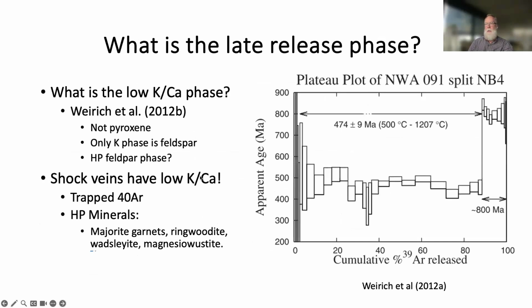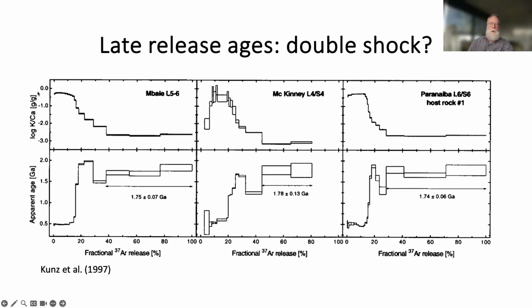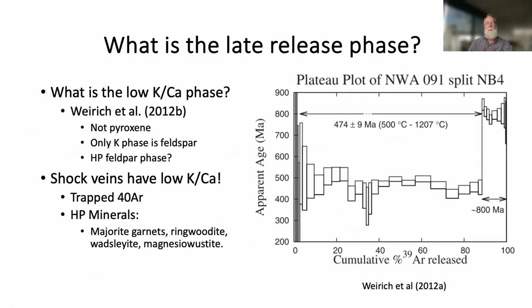A colleague, John Weirich, looked into this. He did his PhD with Tim Swindle, and he was really curious. Well, I should mention, up here is a plot of the log of potassium over calcium. The late release phase is low in potassium relative to calcium. His question is, what is the low potassium calcium phase? I helped him with this. We tried to figure out what it is in these samples. We wrote a paper on it, but it's not in the pyroxene. There's not enough potassium. And we couldn't find any explanation in the feldspar. But I'm pretty sure I know what the answer is now.